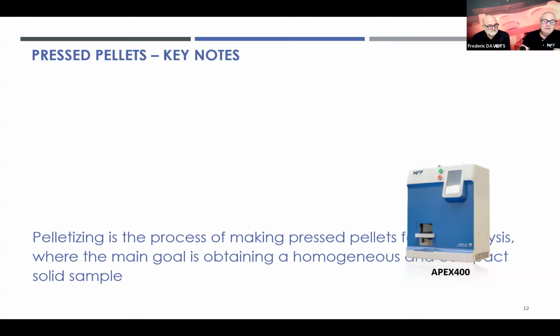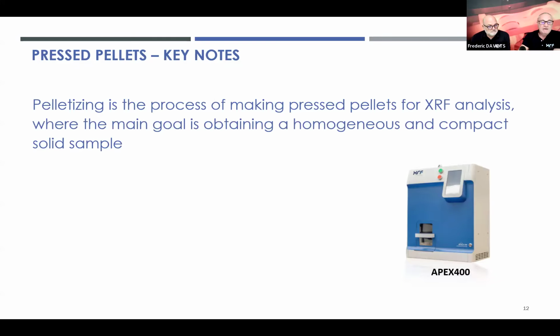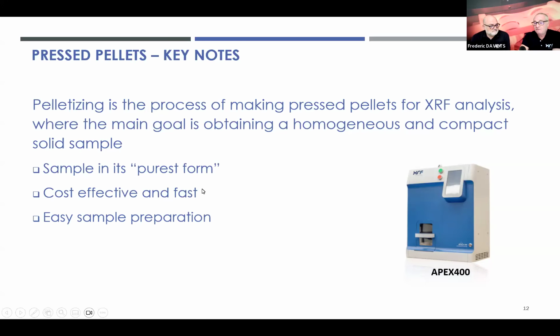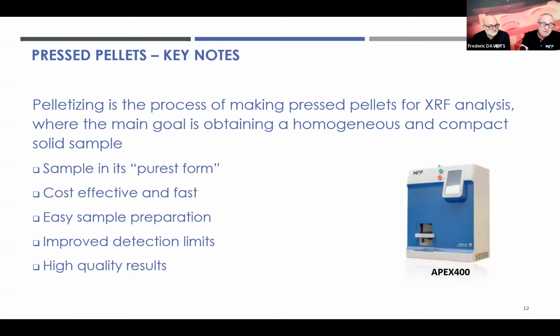for pressed pellets. Well, first of all, the keynotes for pressed pellets are the following. Pelletizing is the process of making pressed pellets for XRF analysis, where the main objective is to obtain a homogeneous and compact solid sample. So homogeneous and compact is very important. Why pressed pellets? Because it is the sample in its purest form. I mean, there is no dilution or almost no dilution. We have it as it is in its natural form, and this is very important. It is also quite cost effective and fast to prepare a pressed pellet, and the sample preparation is really very easy. And we have improved detection limits when we look, for example, at geological samples where we want to analyze trace elements.